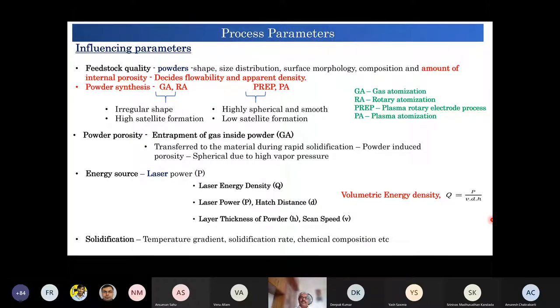And of course, the solidification conditions. When it is melted and then cooled, what is the temperature gradient, under what condition you are cooling, whether controlling is done during cooling or not, and the rate at which solidification is taking place. And of course the chemical composition, because in metallurgy there is a very important term called segregation. Whether the second element, which is inevitably present either intentionally or unintentionally in the material, is sitting at the grain boundary or grain interior, or is uniformly distributed, makes a lot of difference in the properties of the finally processed product.